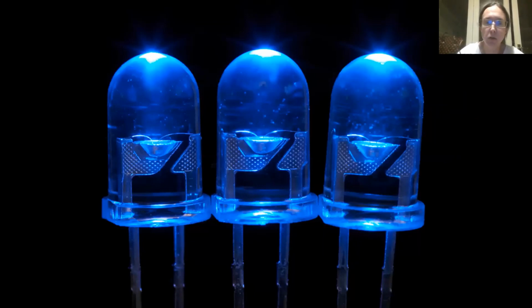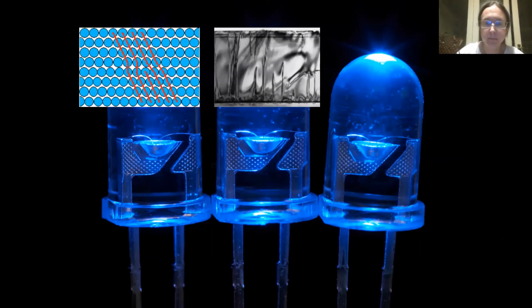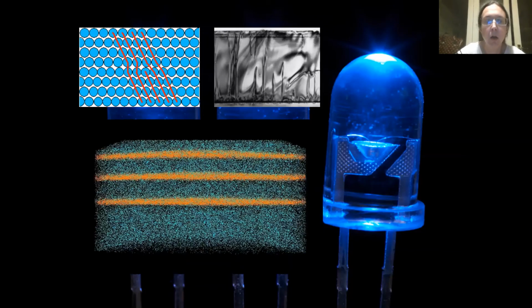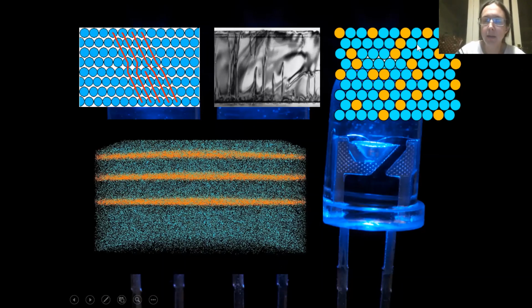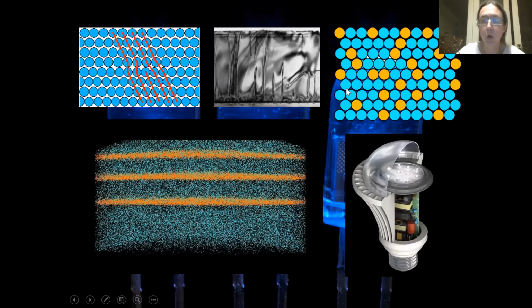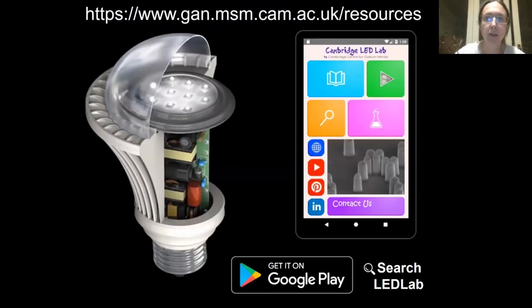Okay, so that was getting really quite in depth into the physics of these materials. But I hope you've enjoyed a tour of what's really going on inside one of these light emitting diodes, right down at the atomic level. We've learned that these materials have defects, but the defects are actually surprisingly unimportant in controlling their performance. We've learned that we can use really advanced microscopy techniques to understand the structures of these materials, and that only when we understand structure properly can we then start to engineer the structure to make even better devices than we already have. We've talked about the fact that indium gallium nitride is a random alloy, but that doesn't make it uniform. That very randomness can be enough to trap our charge carriers, our electrons and holes, and stop them going to our defects. All of that knowledge goes into making the humble light bulb when it's a light bulb made with LEDs.